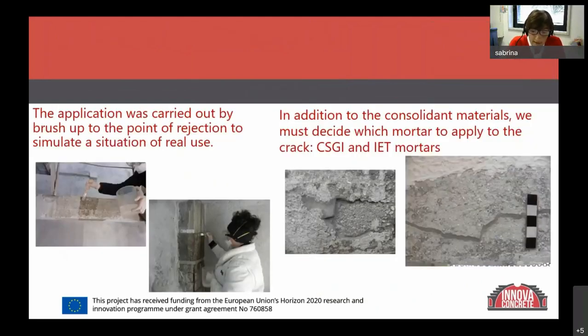The product was applied by brush up to the refusal. This is the most simple and easy method, and it can better simulate the real situation, but not necessarily also the optimum. In fact, during the restoration intervention in situ, the operators do not always have at disposal all the appropriate tools. So the common application by brush can be the only and suitable tool to test the quality of the product and the usage properties.